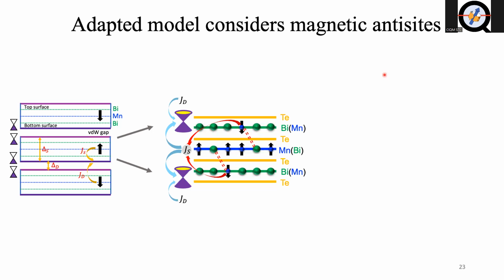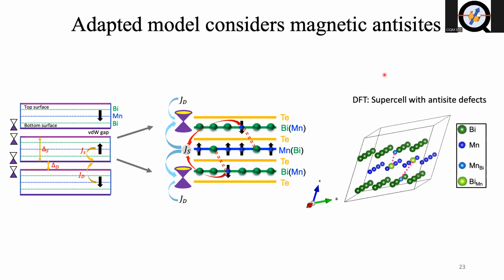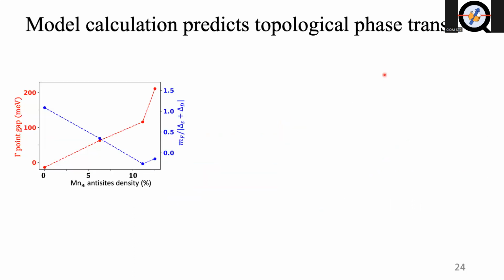But now, how are we going to get those parameters? These parameters should not be the same as those for samples without any defects, right? So what we did is we first carried out the DFT calculation, choosing supercells with some specific number of anti-site defects. And we can adjust the supercell size. We can also adjust the amount of anti-site defects, and then we can simulate the density of anti-sites. Using similar methodology, we can compare our DFT calculation with our model calculation, and then we can extrapolate those key parameters like hopping terms delta S, delta D, exchange coupling terms JS and JD. Okay, so this is our calculation result.